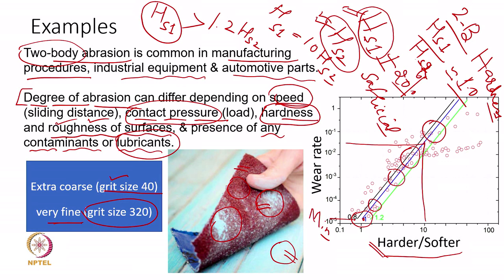If the ratio is less than 1.2 or almost equal, we may find some sort of scratch on both surfaces. So it is important to consider whether the material is going to act as a sacrificial element or not. If both materials are costly and coming into contact, we should keep the ratio approximately equal to 1, and quite possibly we may require some sort of lubrication to minimize the wear rate to a very low value.